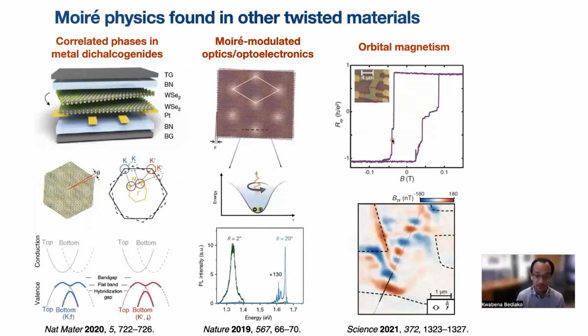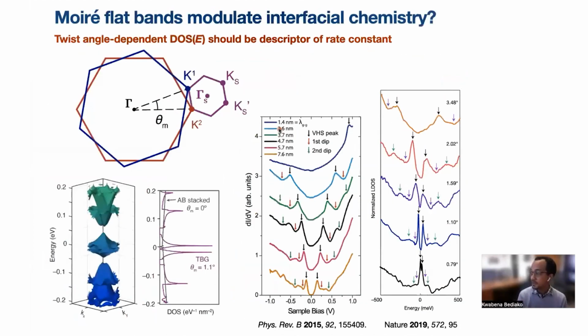Okay, so our question was to ask whether we can use these flat bands to manipulate and modulate interfacial chemistry. And so we looked at the density of states enhancements that we expected for magic angle bilayer graphene, which had been measured as a function of twist angle using scanning tunneling spectroscopy. And we thought back to the role of sulfur vacancies in creating these localized electronic states, in that case within the band gap of pristine MoS2, and started wondering whether these localized electronic states would also serve as reactive hotspots for interfacial chemistry.